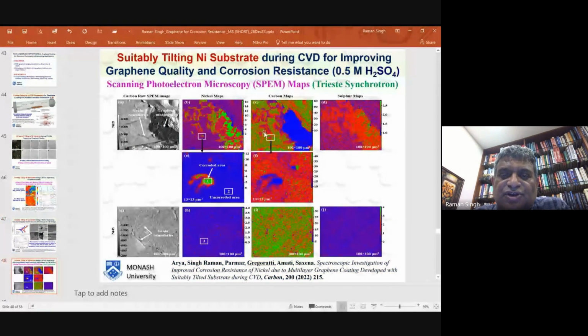We take pride in showing you what I'm showing you now, that for the first time we used scanning photoelectron microscopy. It is nothing but XPS, but instead of getting a simple spectrum for a point, you are doing imaging on the entire surface. And you can see that the 5-degree tilted sample had quite a lot of disrupted area which exposed the nickel substrate, and that's why you can get nickel signals on the 5-degree tilted sample. Wherever you get nickel signal, carbon is not there because the coating was not good enough, and because nickel was exposed to the sulfuric acid environment, you get sulfur signal as well.